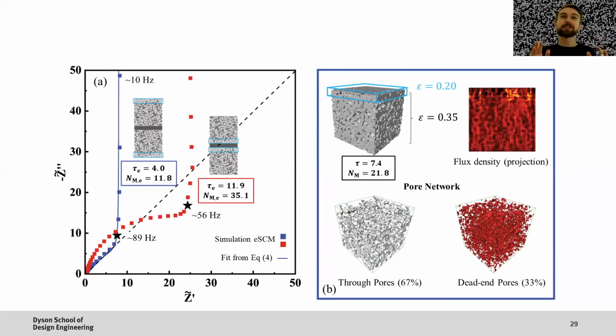And this we are really excited about, because this hopefully will be one of those key metrics that enables us to do some of the in-the-loop optimization of microstructure, where we can say, this metric should really correspond to things that will actually affect performance in a real cell. And so you can hopefully see that each of these potentially seemingly a bit disparate pieces of work are actually coming together towards a process of in silico optimization with metrics that really resemble things that are actually relevant for batteries. I think the other thing that I meant to mention with optimization is, if you just tell it, oh, please maximize surface area, because that will improve your kinetics, then it's just going to make shards, tiny little particles. You want to give it actual constraints that stop it from making non-physical electrodes.